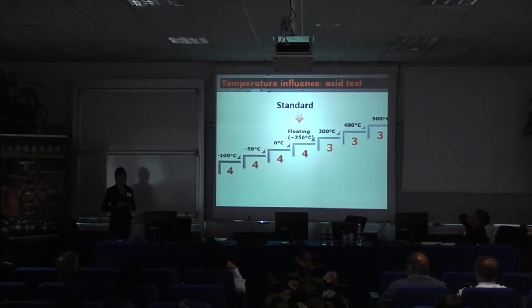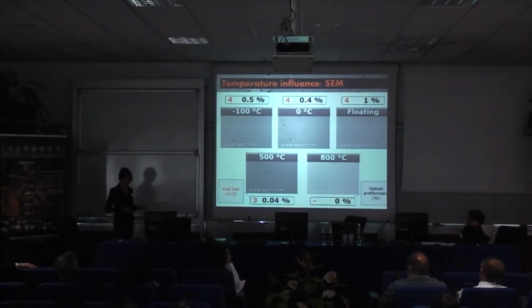We have deposited niobium thin films at different temperatures, starting from minus 100 degrees, obtained by cooling of the substrate with liquid nitrogen, up to 500 degrees centigrade. The standard condition here is something about 250 degrees without heating or cooling. And as you can see from here, when the substrate is heated, you see a decrease of porosity, probably because of some kind of regrowing of the film, because the atoms have higher mobility when the substrate is heated.